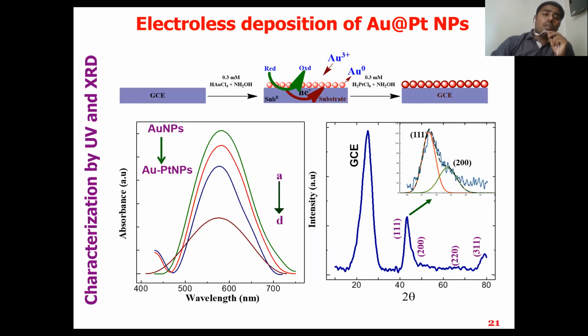Here, the gold-modified GC electrode is immersed into the solution containing chloroauric acid and hydroxylamine, which is a weak reducing agent, and the gold nanoparticles were deposited on the surface of the GCE with the substrate-catalyzed electroless deposition mechanism. After that, the resultant electrode is immersed into the solution containing platinic acid and hydroxylamine, and the platinum nanoparticles were fabricated on the surface.